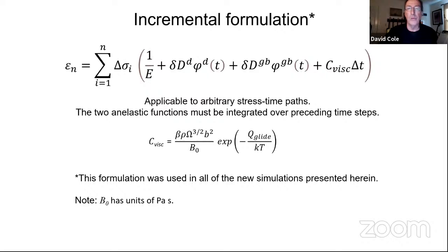You can take these two relaxation processes and basically do this sort of incremental formulation. This is all spelled out in the paper, so I don't need to dwell on it. But basically, if you're going to take this approach, you're basically going to model the behavior over a bunch of time steps, and you need to integrate the anelastic components back to the beginning, more or less, of loading to capture the evolution in the anelastic components. But these are what give you that out of phase behavior.